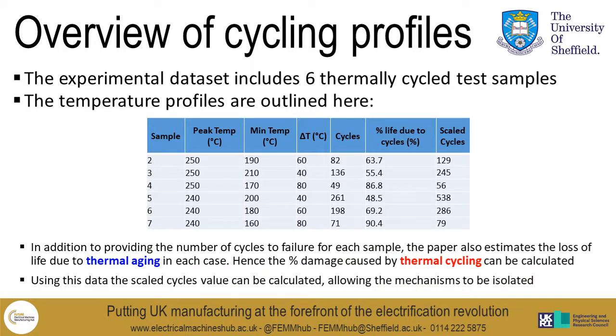Okay, so to give a bit of an overview into the cycling profiles that were used in this work, as I mentioned, there were 6 samples that were thermally cycled. 3 of them had a peak temperature of 250 degrees, and 3 of them had a peak temperature of 240. In each case, there was a sample that was cycled with a 40 degree cycle depth, one with 60 degrees, and one with 80 degrees.